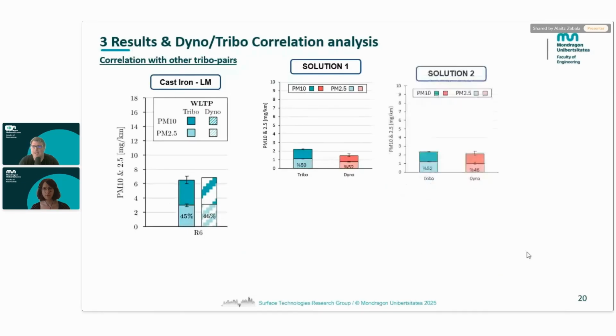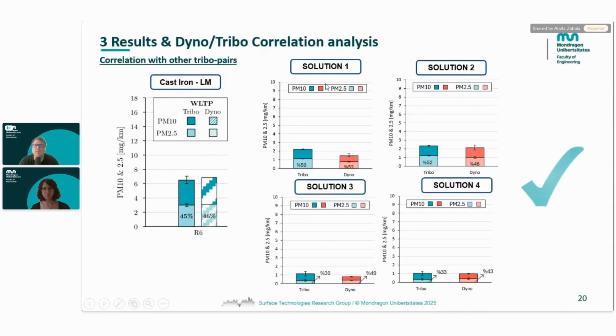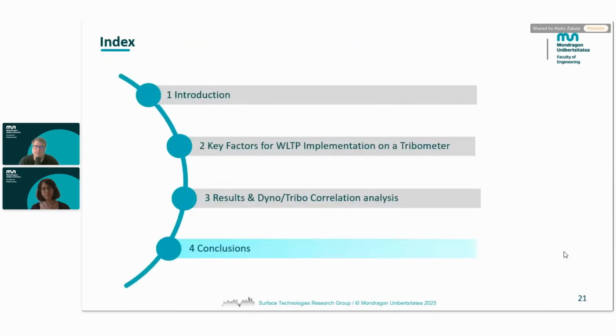Again, this is the cast iron that we compare, and then we can see different solutions. Those different solutions have different particle emissions, and we can see that in all cases the correlation is quite good. The worst that we have is around 20%, which is within the typical difference that we can see in the literature. So we obtain a really good correlation in the tribometer compared to the dynamometer with different solutions. Now, to finish my talk, we can draw some conclusions.